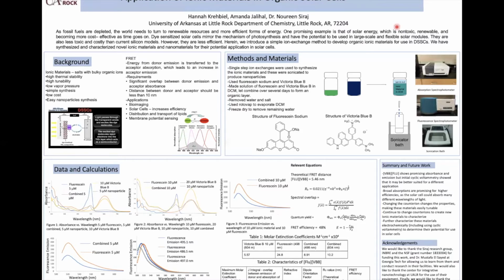And then we wanted to synthesize nanoparticles as they can be used in a wide variety of applications. So we reprecipitated the ionic material in water under sonication to break them down into nanoparticles. Here we have our emission of our nanoparticle. We can see that it retained its peak at a lower concentration. As we increase the concentration, however, the fluorescence goes down, which has to do with the fact that it could be aggregating or quenching.